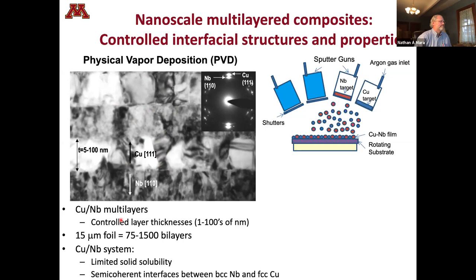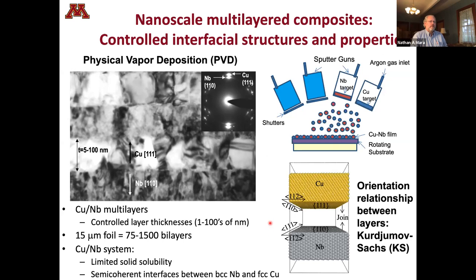We can control layer thickness. We can make these fairly thick for mechanical testing. And the copper niobium system has limited solid solubility, a high positive heat of mixing, and semi-coherent interfaces, which means they contain misfit dislocations, accommodating the mismatch between copper and niobium. And of course, this is our orientation relationship, which we already talked about. It's known as the Kurdjumov-Sachs orientation relationship.